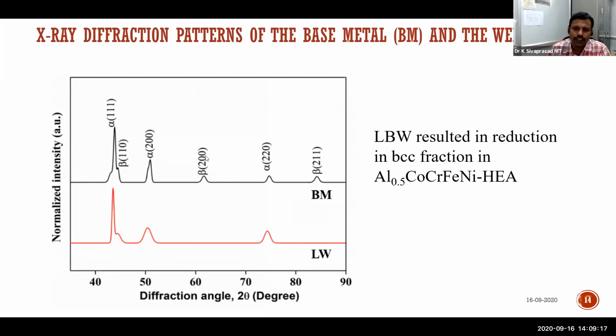And here also, similar to the previous case, the BCC phase was almost completely dissolved in laser welding, which is expected because here melting is faster and cooling rates are also very, very high. So it is expected that the BCC phase could not have evolved.